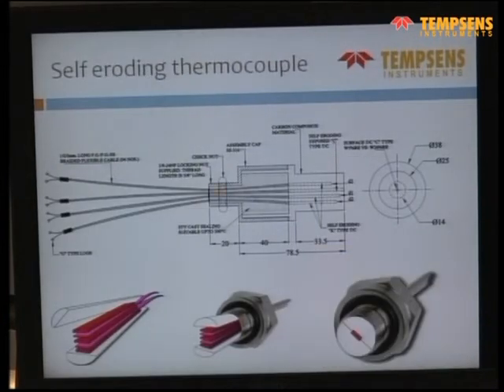We also gave to some customers, like the advanced naval lab, a self-eroding thermocouple. The main advantage of the self-eroding thermocouple is the response time, which is in milliseconds, just a few milliseconds. Here, as the thermocouple is burning off, it is still making contact. It has a layer of insulation. The red one is an insulation layer, and the pink one is the thermocouple, one is plus, then the insulation layer and minus. It is sandwiched between two metal parts, just like a small strip.